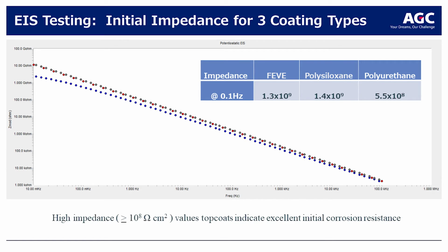Here's an initial impedance run for these three different coating types: the fluoropolymer FEVE, polysiloxane, and polyurethane. Anything over 10 to the 8th ohms per square centimeter is considered to be corrosion resistant. So all three of these coatings initially offer very good corrosion resistance.